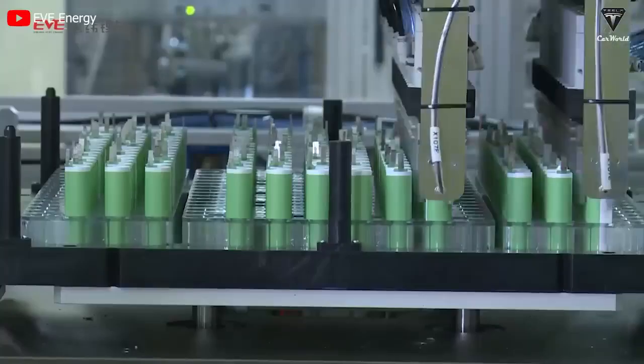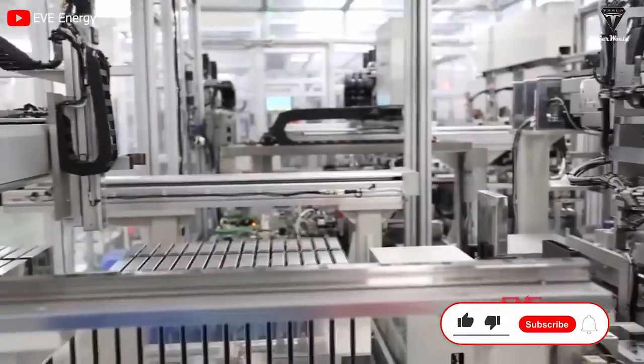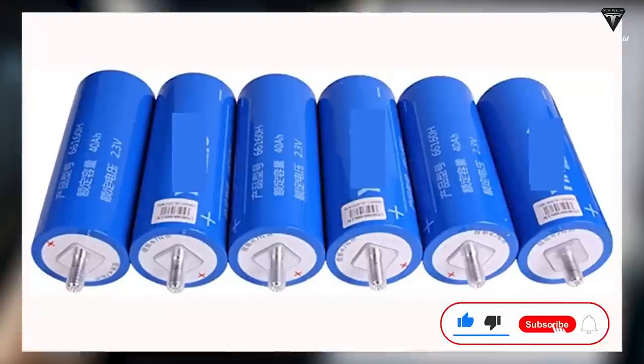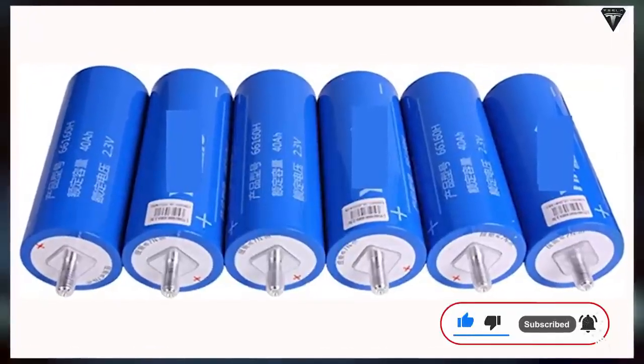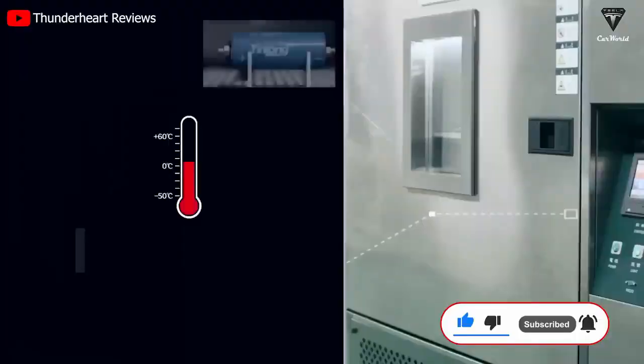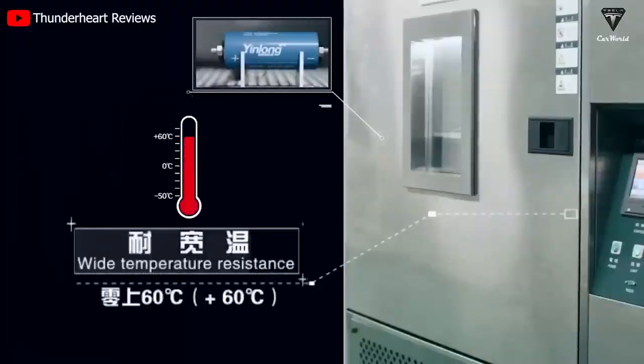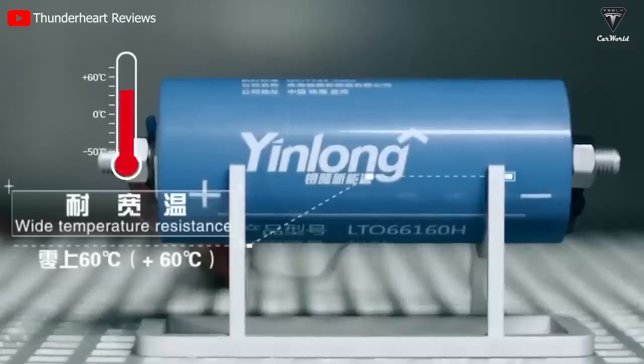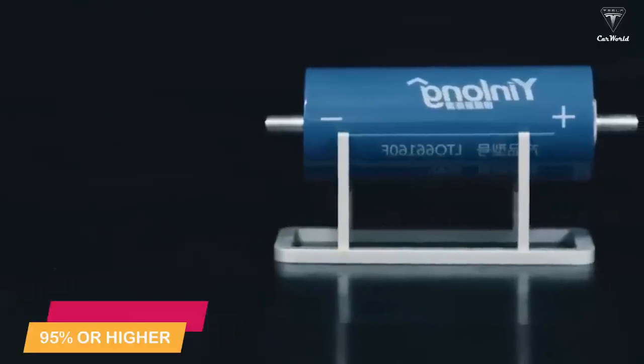The standard lithium battery has no charge and discharge capacity below 0 C and cannot function correctly, whereas the lithium titanate battery has a charge and discharge conversion efficiency of 95% or higher in a temperature range of minus 50 degrees Celsius to 60 degrees Celsius. The performance is significantly better than 95% or higher.